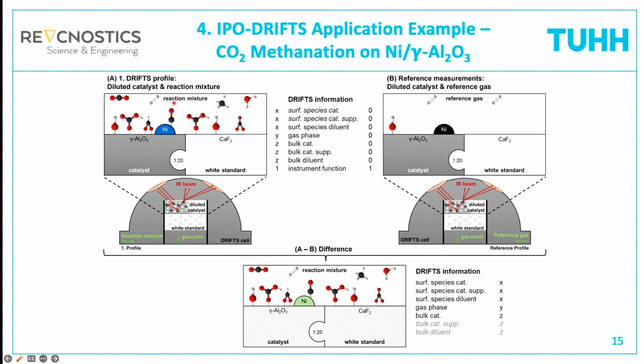So you see on the left side all the things that will absorb IR light in this experiment. And here you see this also in a matrix type of fashion. So first we get absorption by the surface species on the catalyst. Here is something that sits on the nickel nanoparticles. Then we will get absorption by the surface species that sit on the catalyst support. This is here. And then we also get absorptions by the surface species that sit on the calcium fluoride, on our diluent. So all this axis here denotes absorption by surface species, and we denoted this with X because this will change as we go through the reactor.